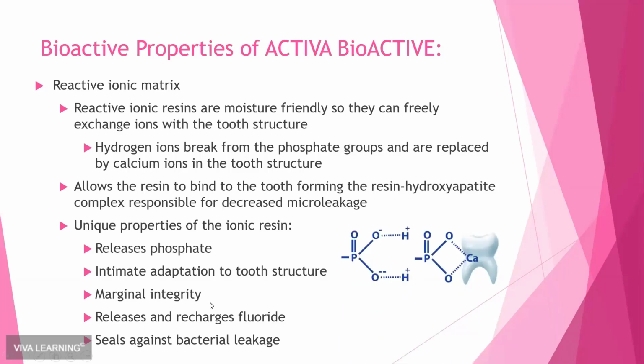So basically what's happening is hydrogen ions, you can see here, are breaking away from this phosphate molecule, which lets the phosphate bond with the tooth, bond to the calcium in the tooth. And this is what's responsible for the decreased microleakage between the restoration and the tooth. This is how the ionic resin is going to release the phosphate, because of that really reactive matrix. We're going to see increased marginal integrity because of this bond, and then that's going to help to seal against bacterial leakage. So in theory, decrease the likelihood of recurrent caries.